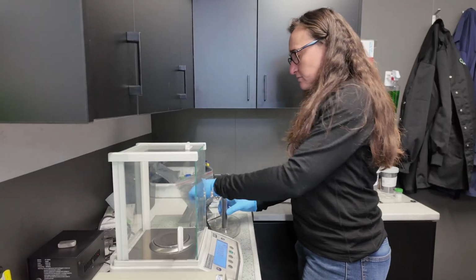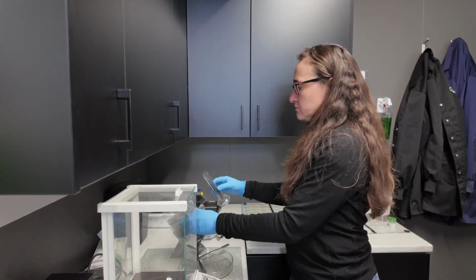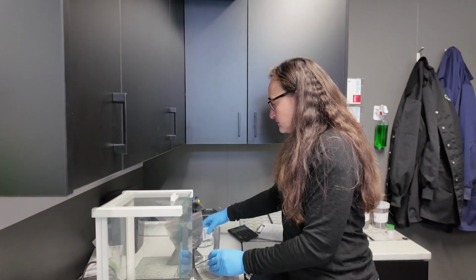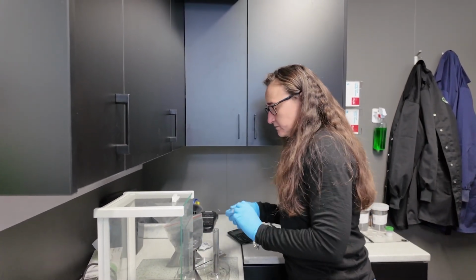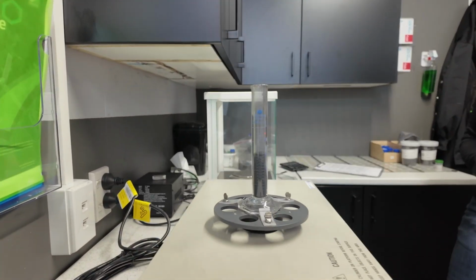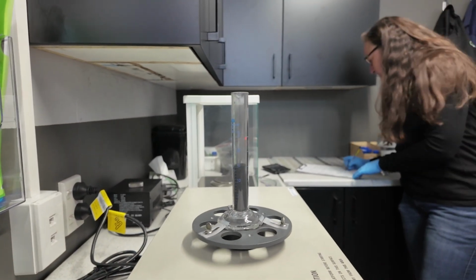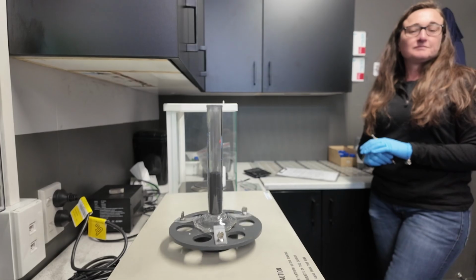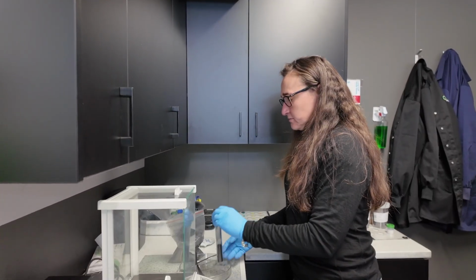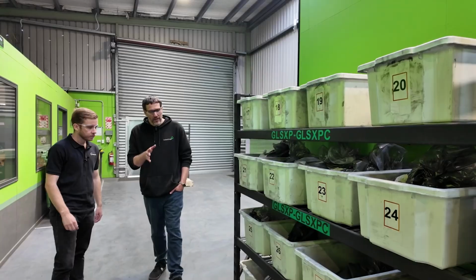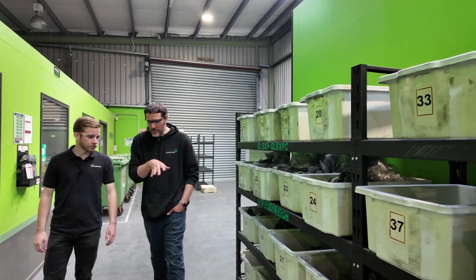And here we have tap density, a measure of how tightly graphite powder can pack. CarbonScape fill the cylinder with graphite, place it into the tap density machine, and let it tap a few thousand times. The change in volume shows how the powder settles, a key indicator of how densely an anode can be packed. And here we come to the final product storage area.